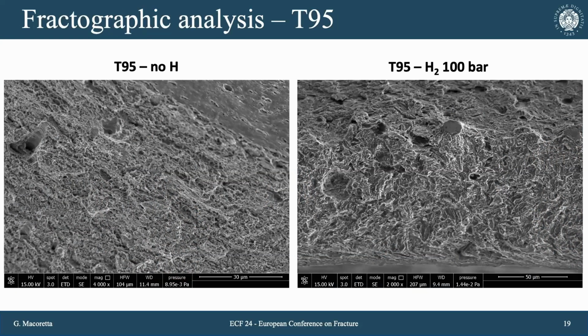If we look at what happens in terms of fracture surfaces, on T95 without hydrogen we see a standard ductile surface with microvoid coalescence, a bit different from the previous one because of the increase in carbon content. This is the internal edge of the hole in the specimen, and when we introduce hydrogen, at least in the portion nearest to the hole, we see a strong transgranular fracture. So there is a strong change between the hydrogen-free and the hydrogen-charged material, showing the effect of hydrogen and the embrittlement effect.